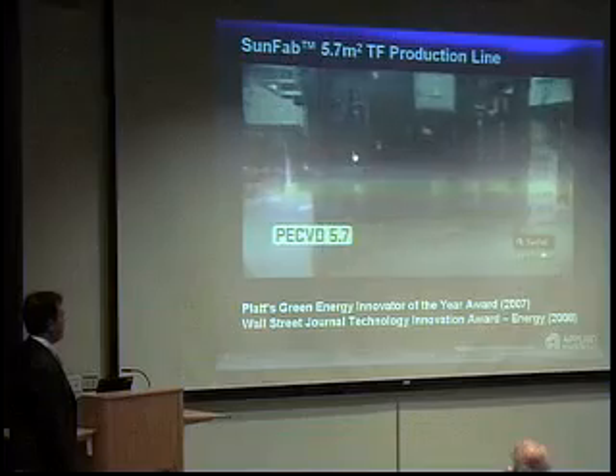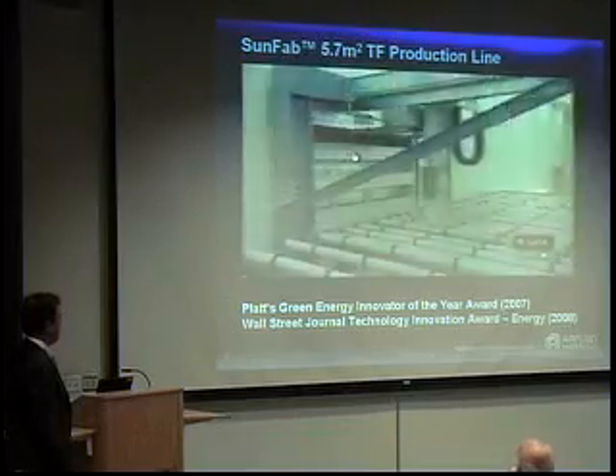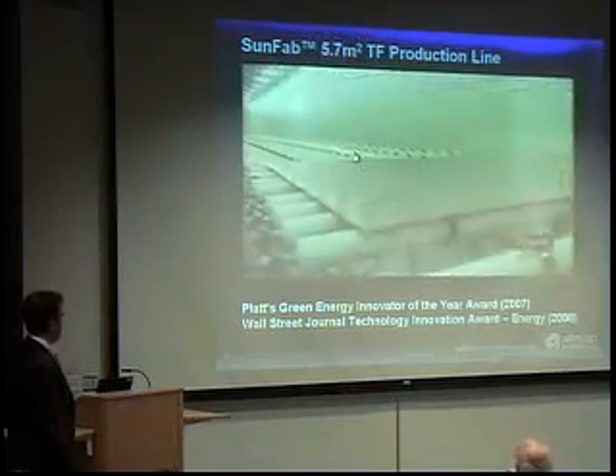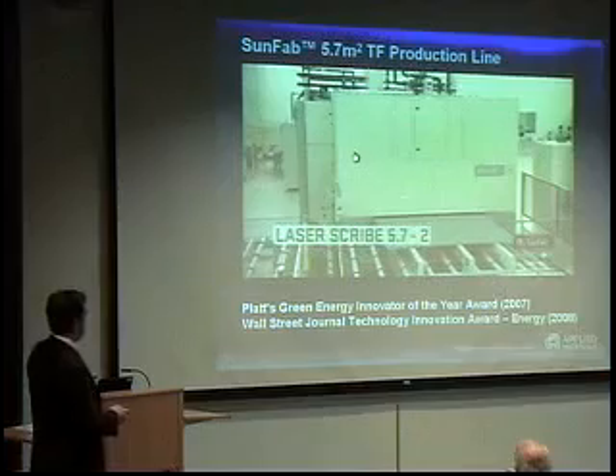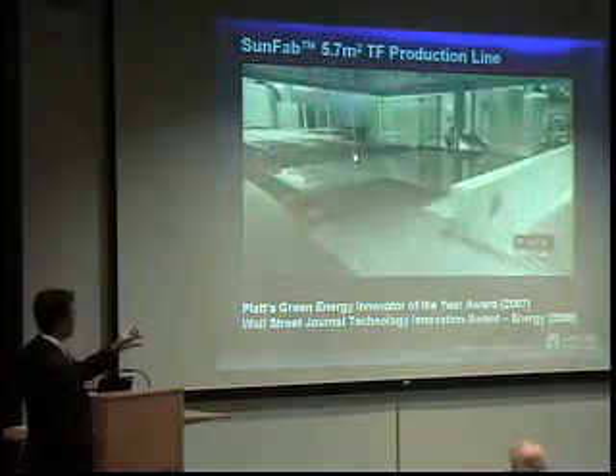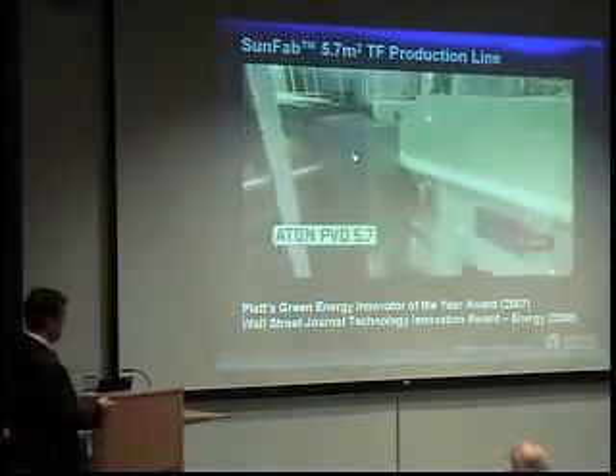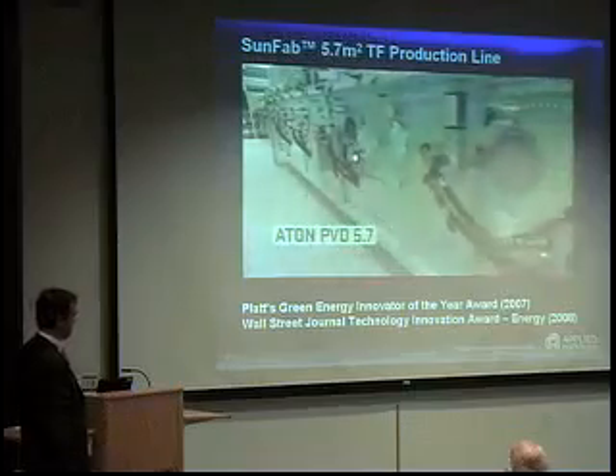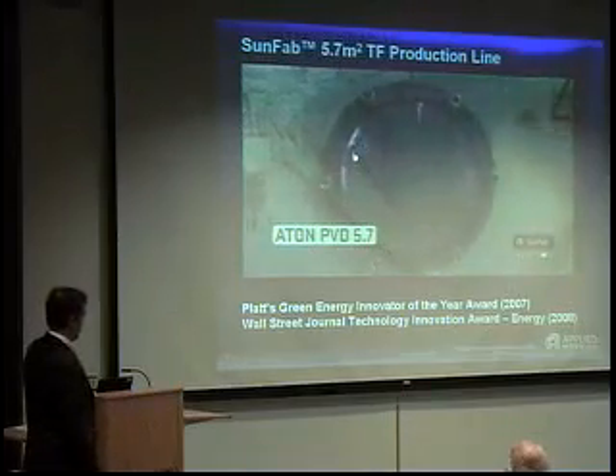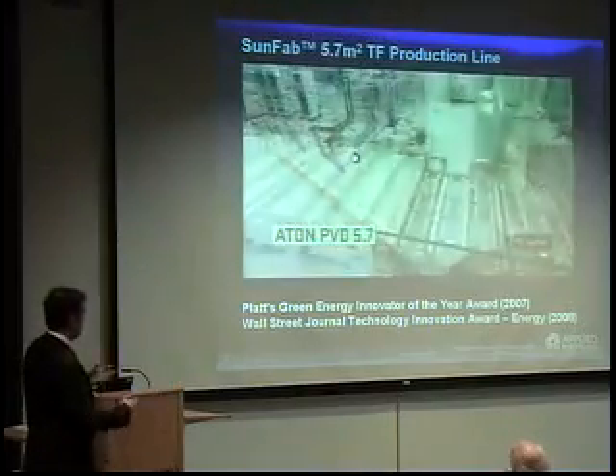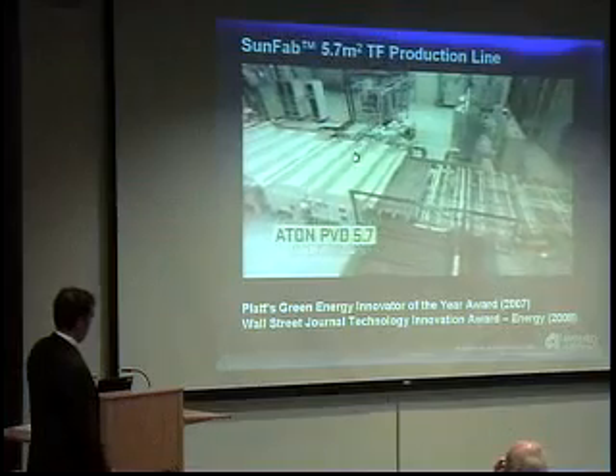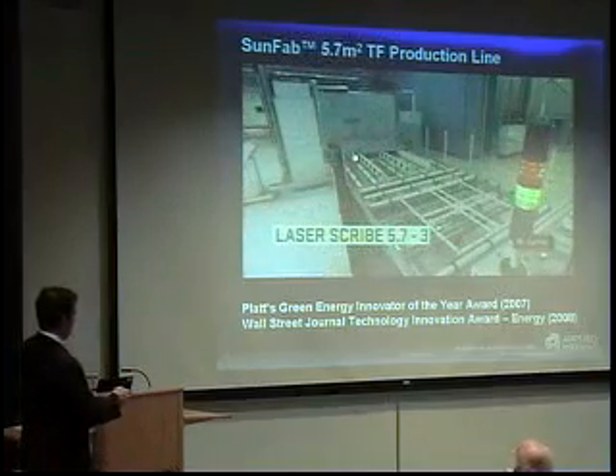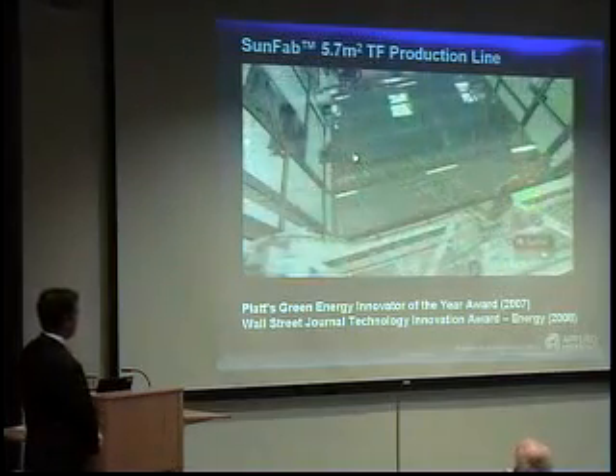It's done with plasma-enhanced chemical vapor deposition, different kinds of silicon. I'll explain that shortly. Comes out. This is a simple model. You then pattern the actual solar cell itself, the silicon. You then put the back metal on, aluminum, some alloys. This is in a modified glass coater, like I showed before. You pattern the metal layers.